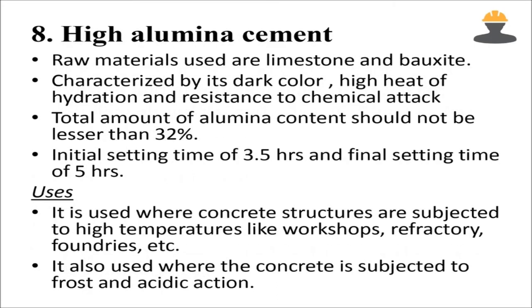High alumina cement uses bauxite as the main raw material. It has a dark color and a high heat of hydration. It provides resistance to chemical attack. The alumina content is around 32%. The initial setting time is 3.5 hours and the final setting time is 5 hours.